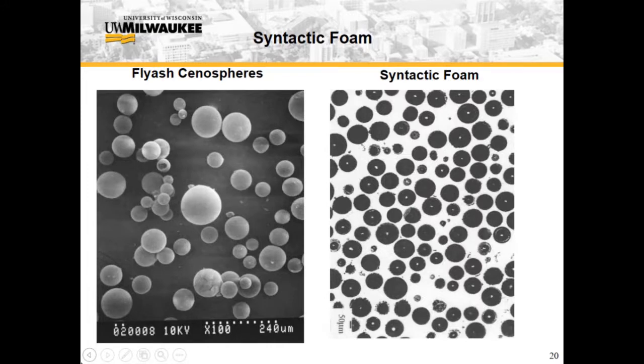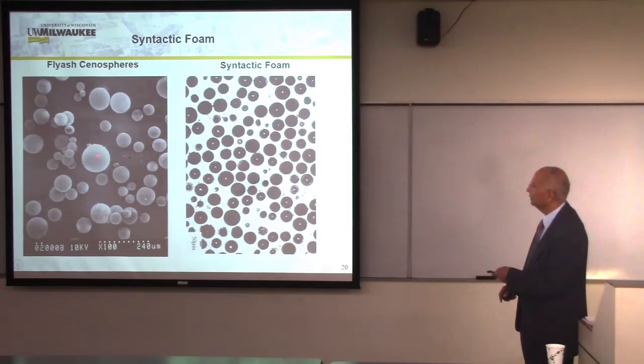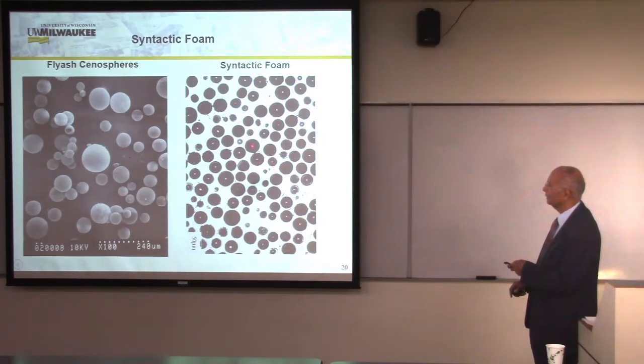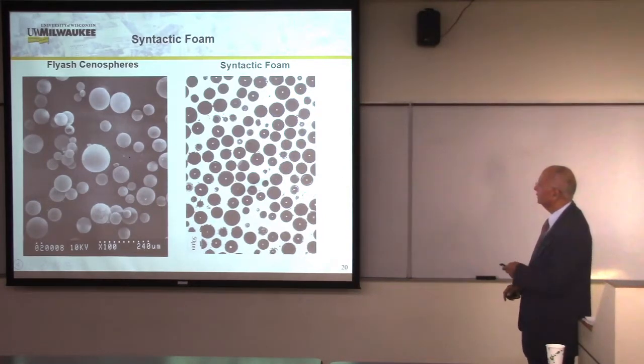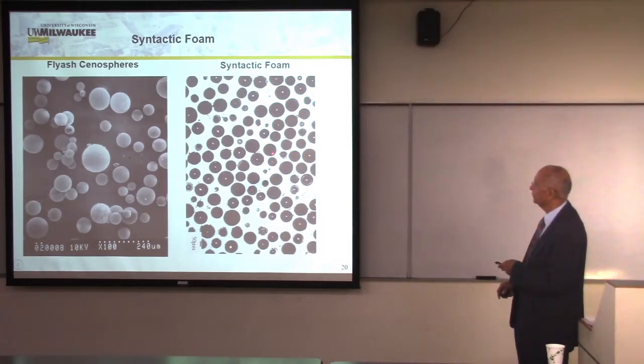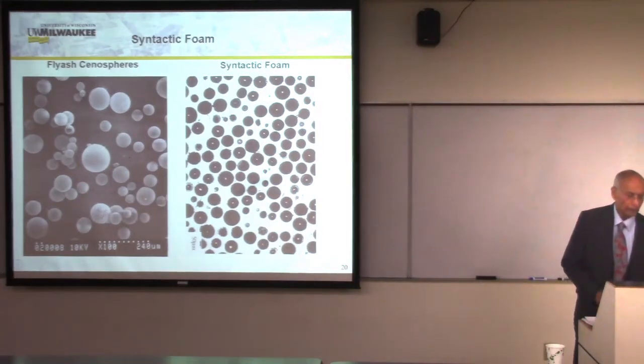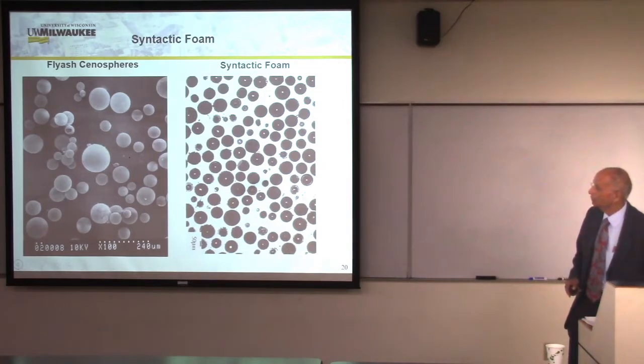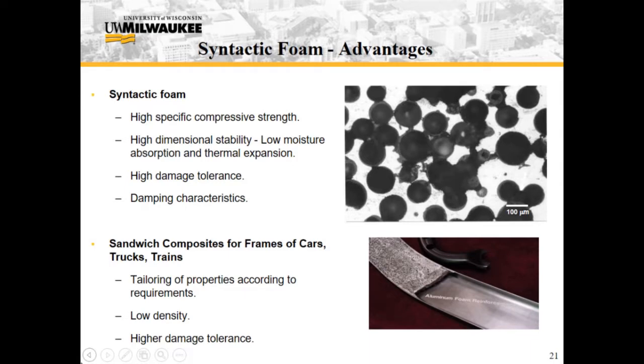India produces about 80 million tons of fly ash which is wasted each year, only a small fraction is used for construction purposes. 2% of this fly ash is perfect hollow spheres, which we call cenospheres. So this is a typical cenosphere, and by simple infiltration technique, I can produce a 65% volume percentage hollow spheres of fly ash embedded in aluminum. That is the picture. So this is a syntactic foam casting, and the energy absorption per unit weight of this casting is much more than solid aluminum or aluminum foams that are currently being used. So there is a great opportunity to manufacture these castings for both civilian and defense applications.